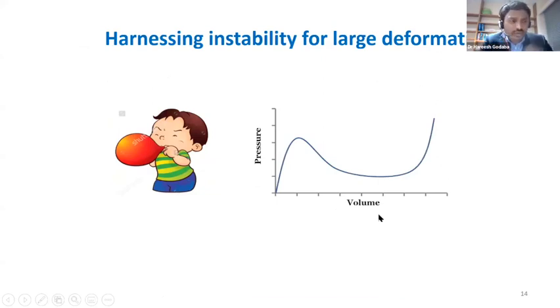But the clue to how to even harness this type of instability to achieve large deformation is in the mechanics of elastomer balloons. If you remember the last time you tried to inflate a rubber balloon, maybe as a kid, you would remember that initially this type of balloon is very difficult to inflate, but then once you begin to inflate it with some air, it becomes very simple. It becomes quite soft, and then finally it begins to become stiffer again. That is because the PV curve, or the pressure volume curve of these balloons, is also N-shaped like this. At some intermediate volumes, the pressure required to sustain or to increase that volume is very, very low, which is why it is quite easy to inflate a balloon in this intermediate volume state.